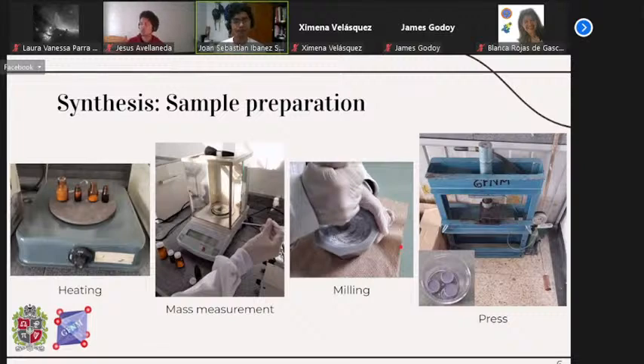So before we could apply the thermal process, we needed to perform a sample preparation in order to increase the probability of the reaction. Firstly, we heated the precursor oxides to remove the humidity that they accumulated because of hygroscopy, I believe. Taking into account that we expected to have a perovskite as a final product, we measured the masses of the precursors in order to synthesize a gram of the CaLaTiFeO6 sample. We ground the mixture inside of an agate mortar for 3 hours to ensure an increase in the surface contact. And we also made pellets with our powder, applying forces up to 50 kilonewton.